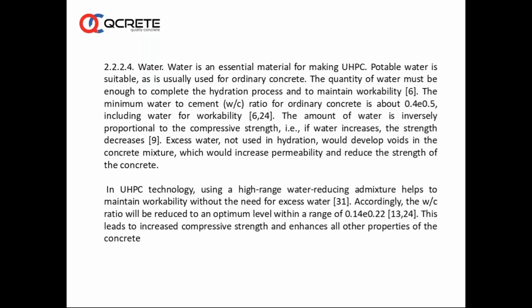Water is an essential material for making UHPC. Potable water is suitable, as is usually used for ordinary concrete. The quantity of water must be enough to complete the hydration process and to maintain workability. The minimum water to cement ratio for ordinary concrete is about 0.4 to 0.5, including water for workability.